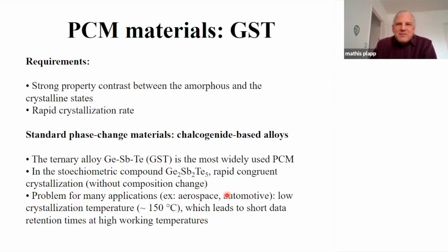So that means that PCM materials must fulfill certain requirements. As I have said, if you want to read them out well, they must have a very strong contrast in some properties between the amorphous and the crystalline state. But at the same time, for the memory to be fast, they must crystallize quite rapidly. And in principle, these are contradictory requirements, because usually, if you want a strong property contrast, you also need a strong contrast in structure. And if you have a strong contrast in structure, the kinetics of crystallization will be slow.